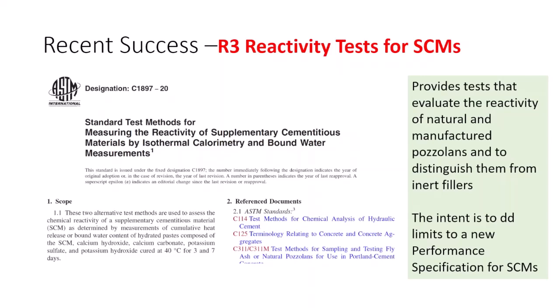A lot of the specs we have, like C618 for fly ash and natural pozzolans, uses a strength activity test that, although it's okay with fly ash because we have a history of using fly ash, we sort of know what it does. I can take ground sand and make it pass the strength activity test in C618. That's not a very ringing endorsement for the reactivity, so we developed a reactivity test as part of a RILEM committee I was involved with, and I championed this through the ASTM system to get this reactivity test, the so-called R3 tests, using isothermal calorimetry as one method and just bound water measurements as another, to evaluate whether pozzolans are actually reacting.